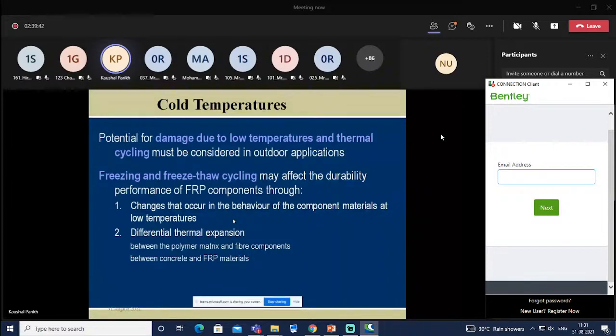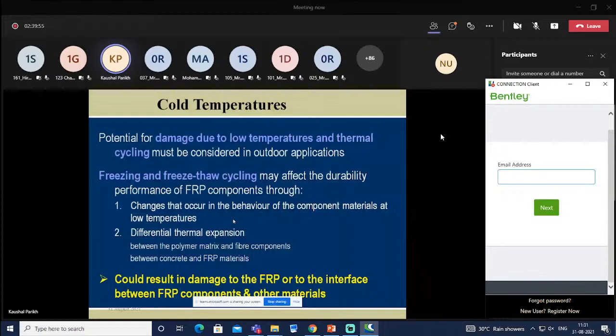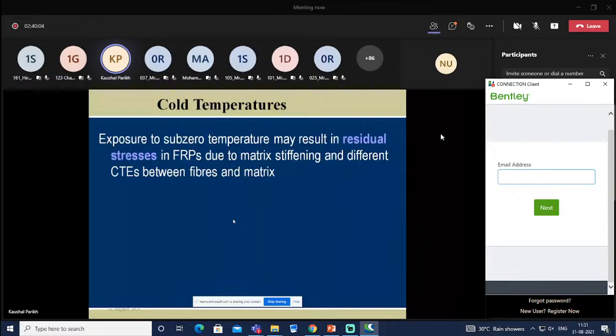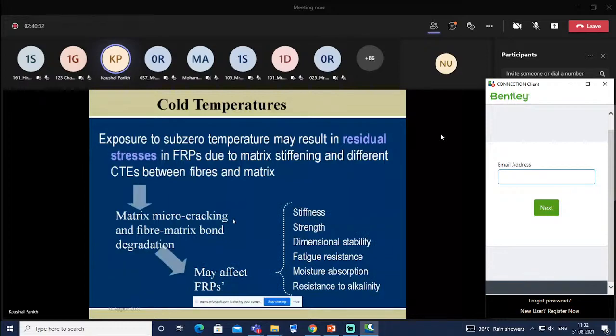Also, the differential thermal expansion between the polymer matrix and fiber components is one of the important issues. So, the cold temperature could result in damage to the FRP or the interface between the FRP components and other materials. It is to be noted that structures exposed to sub-zero temperature may result in residual stresses in FRPs due to matrix stiffening and differing properties in the cold temperature environment between the fibers and matrix. Because of that, matrix microcracking and fiber-matrix bond degradation will occur, and they may finally affect FRPs in terms of stiffness, strength, dimensional stability, fatigue resistance, moisture absorption, and so on. So all these things will be affected because of the exposure of the structures to sub-zero temperature.